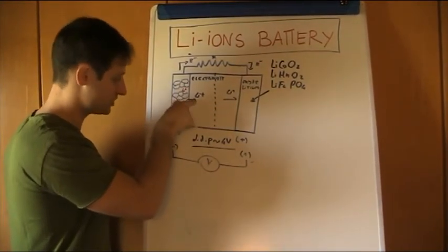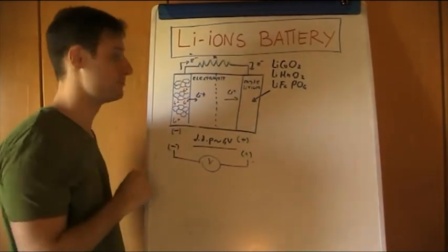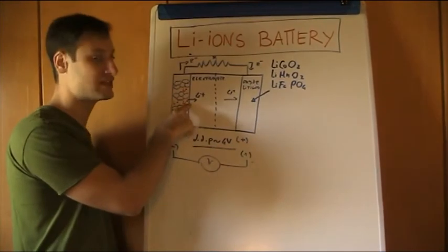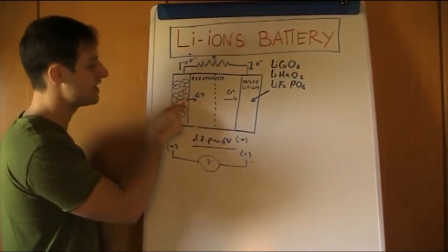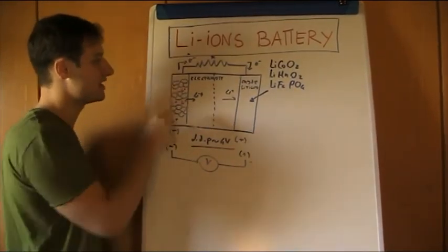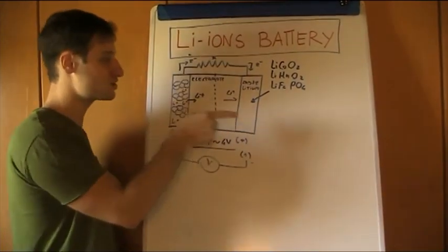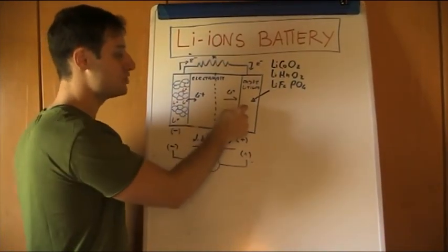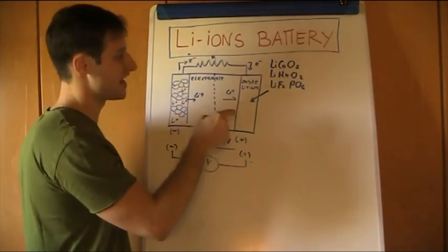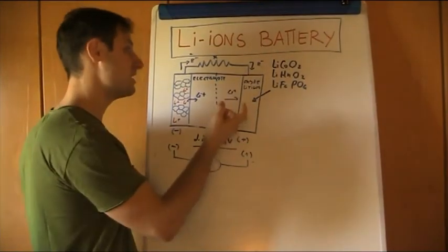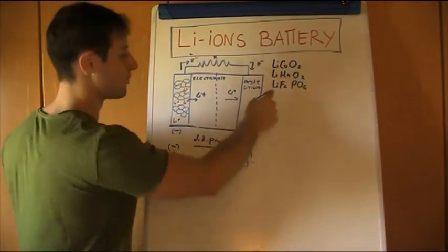Basically, with an oxidation process here and a reduction of the metal, not the lithium, that is important. So here we have an oxidation of the lithium during this step. The lithium passes from lithium zero, intercalated, to lithium plus with the release of electrons, which is the oxidation. And in this case, electrons are collected and we have intercalation of lithium. But what is reduced is not the lithium, because lithium remains as lithium 1 plus inside the oxide, because it's stable. What is reduced in this case is the corresponding metal, cobalt, manganese, this one.